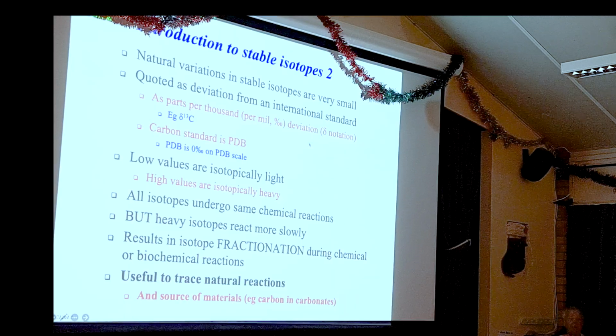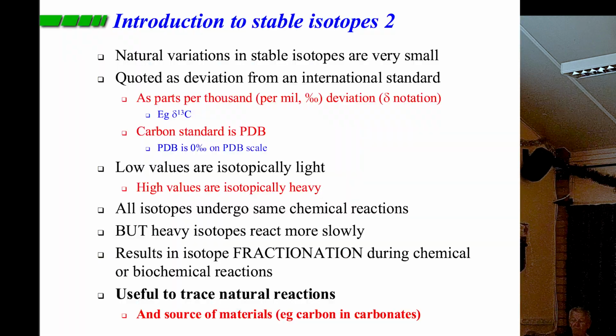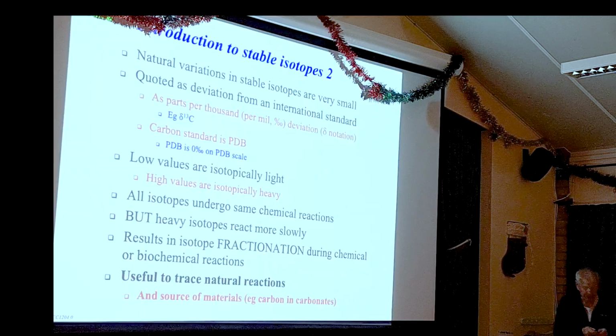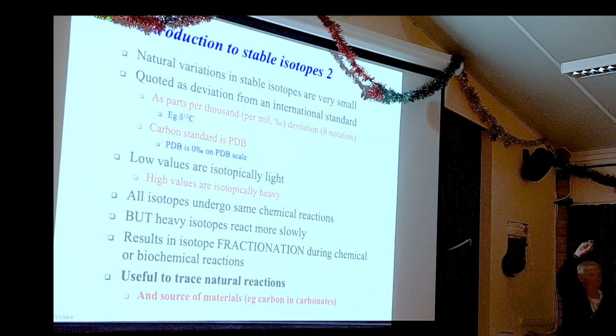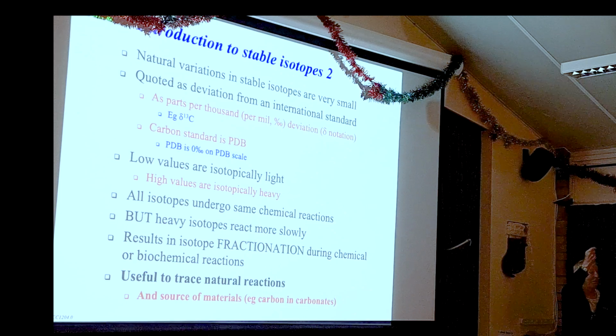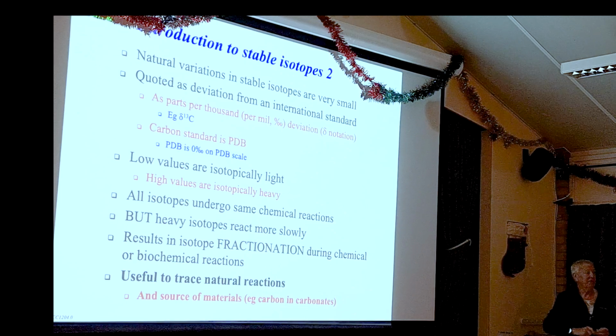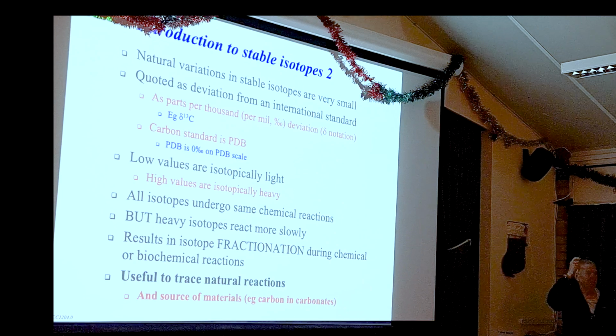Now, these natural variations in the amount of carbon 13 relative to carbon 12 are really quite tiny. So what we have to do is compare the ratio in our sample with an internationally accepted standard material. And what we do for carbon is our international standard is one of these, which is a fossil belemnite. We call it the PDB standard because this belemnite comes from the Cretaceous Pee Dee formation in South Carolina.